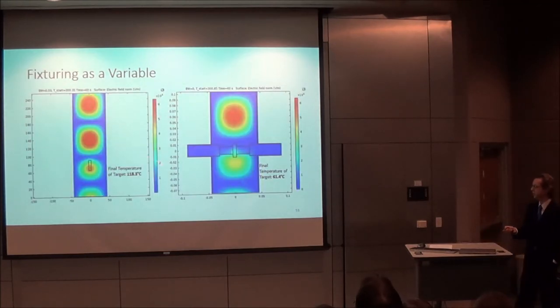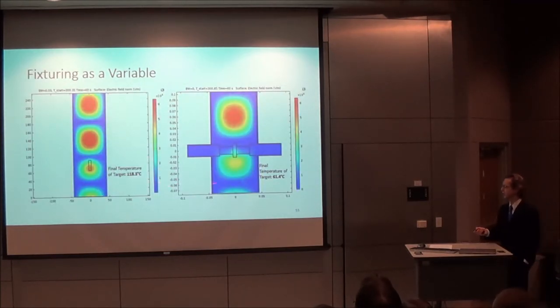In addition, the effect of the joint fixture is significant. Anything we put in the waveguide is going to affect the coupling of the target and the wave. So using the same parameters here, with only the back wall varied between them to get maximum heating in the target for each situation, these are experimentally determined final temperatures, and they vary by a factor of 2 solely because of distortion caused by the pressure fixture in the waveguide.